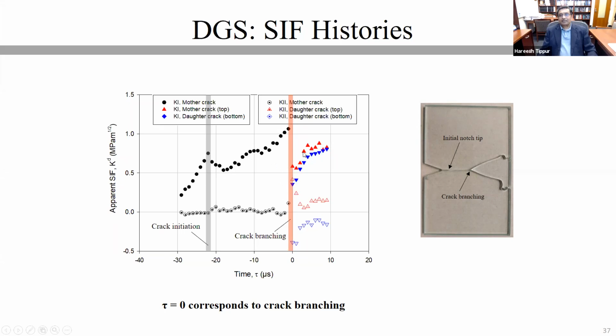The solid symbols, the upright triangle, are for the upper branch, and the inverted triangles are for the lower branch. The open symbols in this chart are always for the mode 2 stress intensity factors. They are negligibly small for the mother crack. And then once the mixed mode branches form, the two daughter cracks form, you have some constant value of K2 towards the end of the fracture event that we were able to capture.